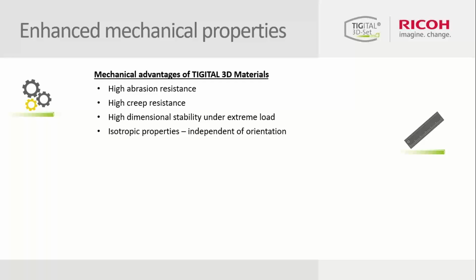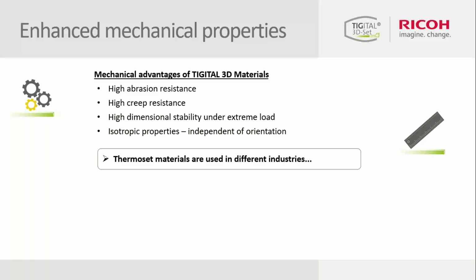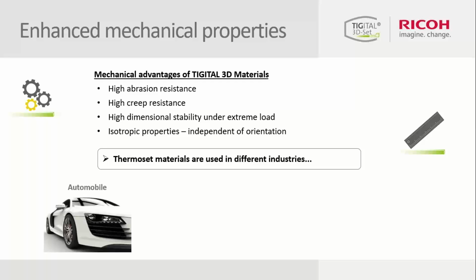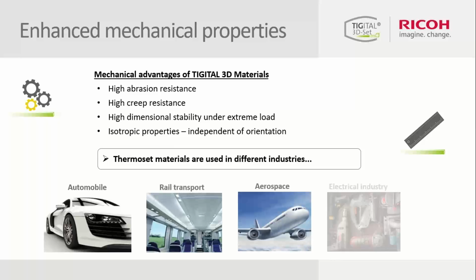And this kind of performance is achieved thanks to the chemical cross-linking happening during the printing process, and it is enhanced by the post-processing step required to fully cure the materials. Also, these properties can be easily adjusted and customized by playing on the material formulation, but also on the printing parameters, so we can really fine-tune and tailor those properties and make them suitable for specific applications. So thanks to these properties, this material can be used for very demanding applications in several sectors, such as automotive or railway, aerospace, as well as the electrical industry.